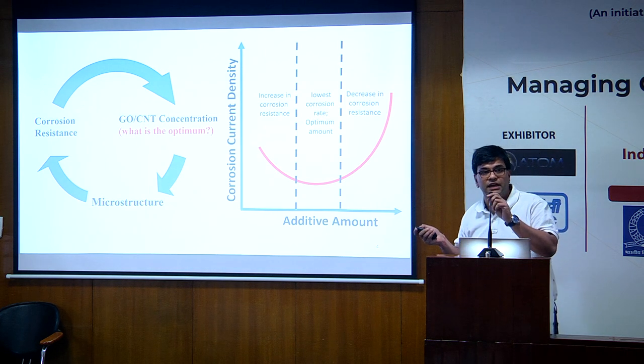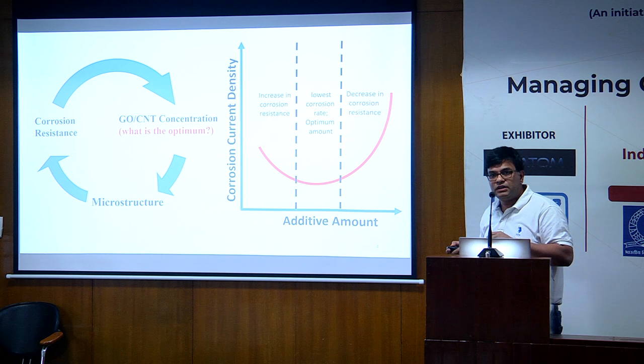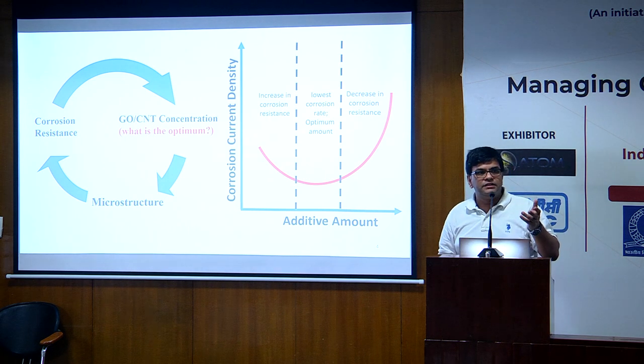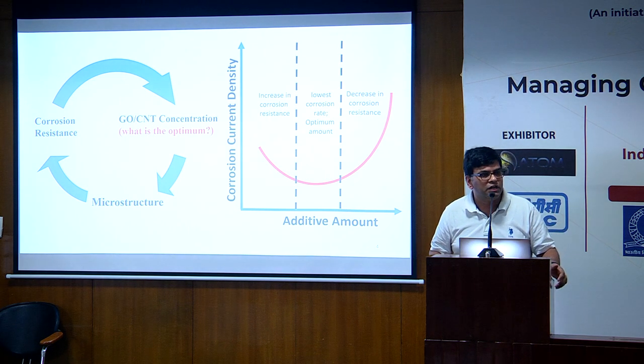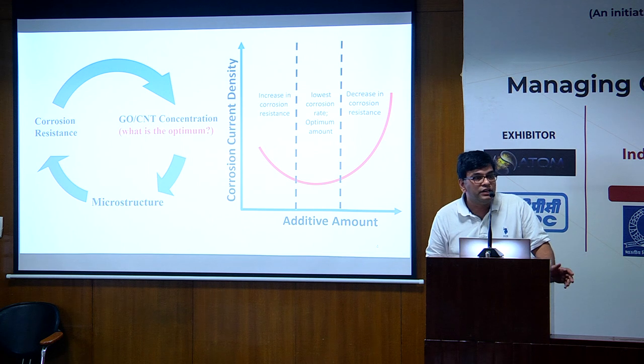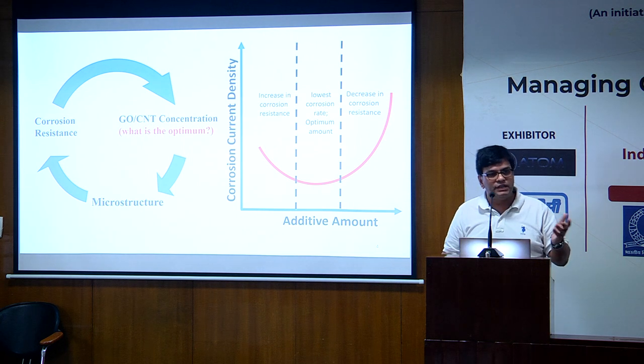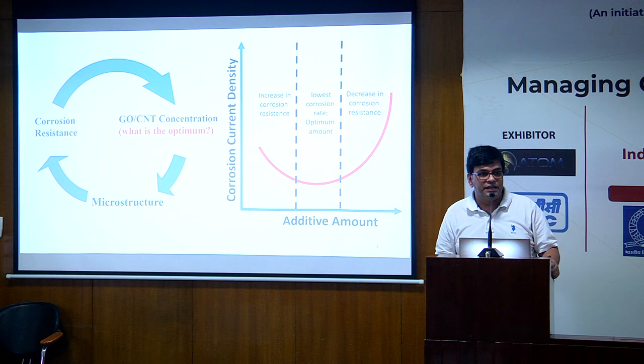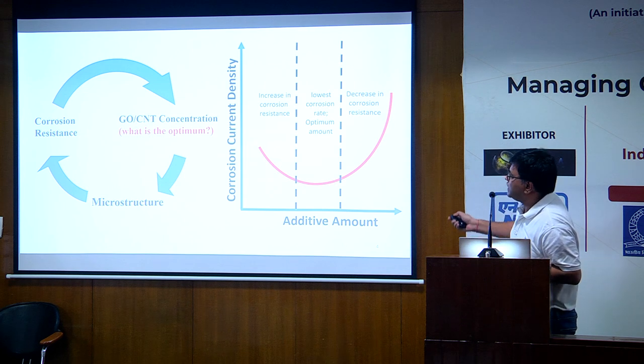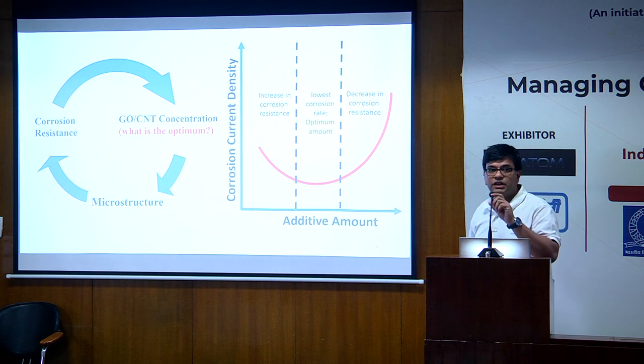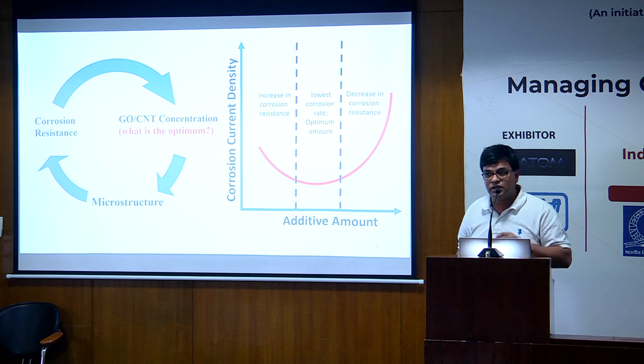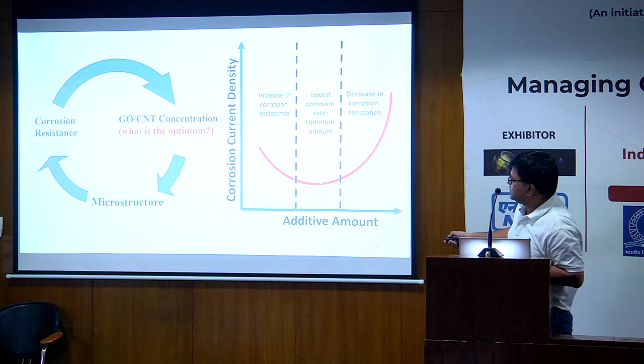and then after a certain optimum additive, the corrosion rate increases very, very rapidly. In principle, things like graphene oxide or carbon nanotube are basically carbon, so they are cathodic with respect to the metal in which they are being embedded. So if you go to a very high concentration range, the problem is very high galvanic coupling, where carbon is cathode and metal is anode.